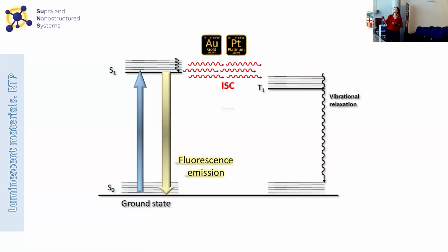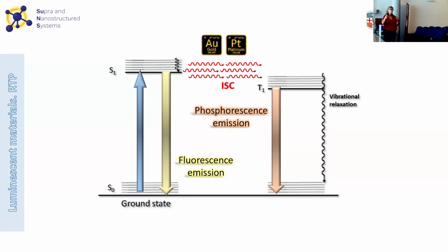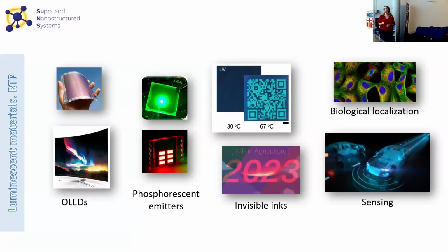This is what is called the heavy metal effect. So with this heavy metal effect, this intersystem crossing, we can have, for example, phosphorescence when the electrons go to the ground state emitting light. Okay. And this is what we use. This is one of the reasons that gold and platinum are relevant for this, favoring the population of the triplet excited state. And we are interested in that since they can have several applications in some different areas, like those here presented. In some of them, we are working, let's say, more autonomously, and others in collaboration with experts in the field.